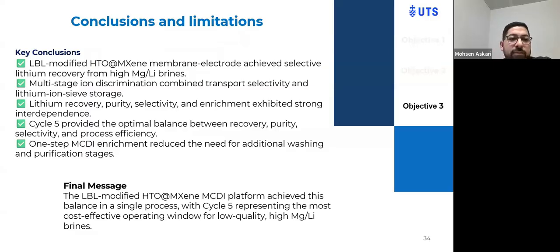As a conclusion, the LBL-modified HTO@MXene membrane electrode achieves selective lithium recovery for high magnesium-lithium brine, with multi-stage ion discrimination combining transport selectivity and lithium ion sieve storage. Lithium recovery, purity, selectivity, and enrichment exhibited a strong cycle dependence, and cycle 5 provided the optimal balance between recovery, purity, selectivity, and process efficiency. The one-step MCDI enrichment reduced the need for additional washing and purification stages, and it can be a cost-effective method, a fast and highly efficient process for lithium enrichment.